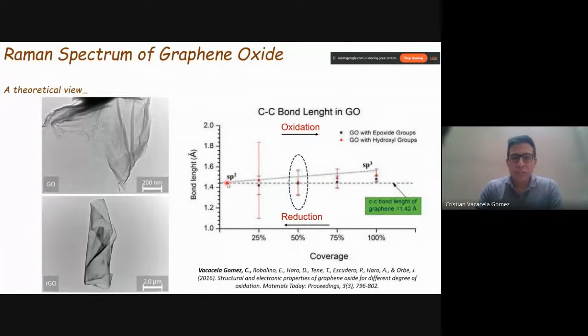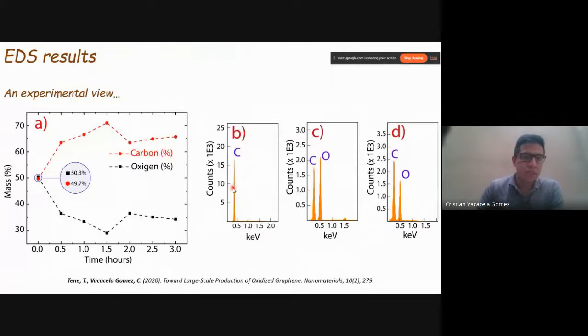In other terms, oxidation moves toward sp3 hybridization, and reduction moves from sp3 hybridization back to sp2 hybridization. That is the idea. So oxidation moves to the right side and reduction to the left side, in order to modulate different hybridization properties. And just to comment, here is the elemental analysis. Without any reduction process, our pristine graphene oxide offers 50.3% of oxygen, and similar for the carbon, so 50-50 more or less.